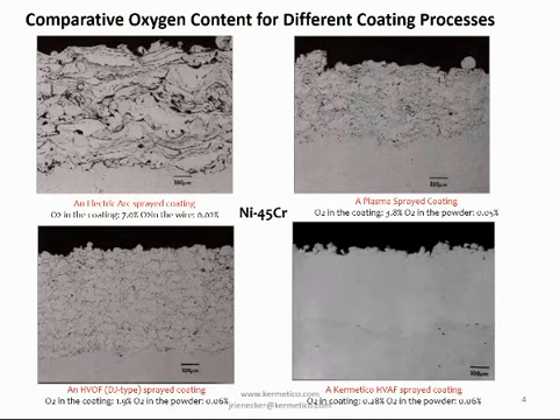Plasma started out with 0.05 oxygen content in the feedstock powder, only slightly higher than the arc-sprayed coating, but the oxygen level in the as-sprayed coating is only 3.8%, just slightly above half that of the arc gun coating, and that too is apparent from looking at the micrograph.